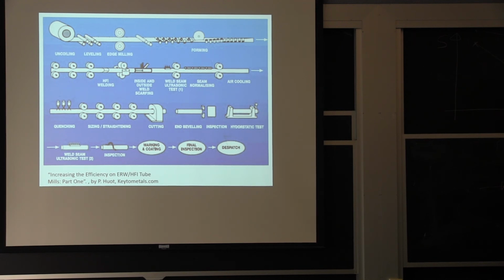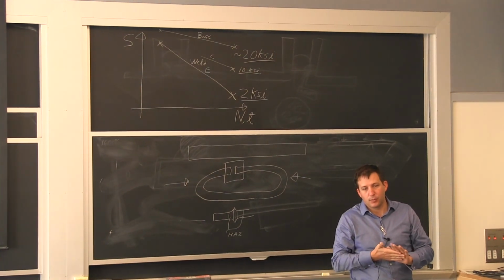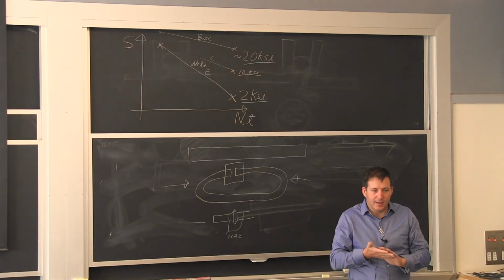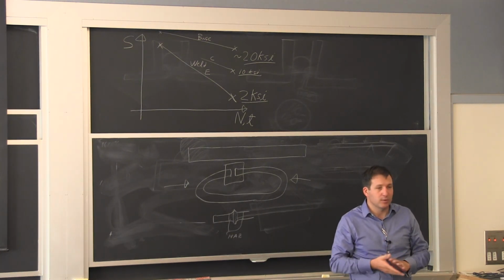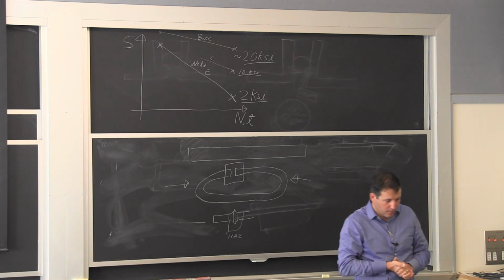So depending on your application, what you're trying to do, whether corrosion is a problem, whether the fatigue resistance is a problem, you may or may not care too much if you have these weld seams, because you can do them in very controlled conditions. This is a very efficient process, and it's easier to inspect. When I was talking earlier about making the complex joints for the roof joists, there's no easy way to inspect, but here, if I'm just taking a flat plate and turning it around, I can apply a non-destructive technique and continuously monitor whether there's a problem with my welded seam. So cost and the ability to do a lot of quality control are the two main reasons why we use welding a lot for pipes.